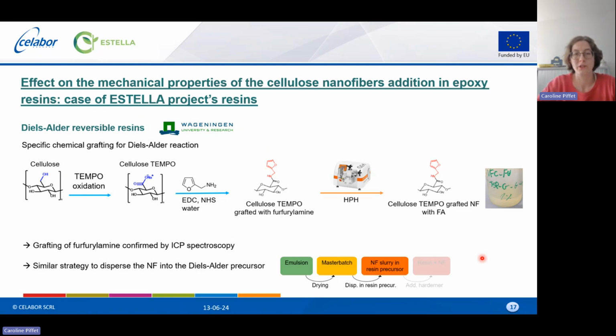Then the second case of transposition of our developed method is with the Diels-Alder reversible resins from Wageningen partner, and we had to adapt our specific chemical grafting. So first, we started with the same functionalization with carboxylate group, and then we proceeded to a second chemical treatment to graft furfurylamine groups on the cellulose. With the ICP spectroscopy and the IR spectroscopy, we confirmed that we have nearly 100% of the cellulose of the tempo oxidation that is transformed after that in furfurylamine on the cellulose chains, so very high grafting ratio.